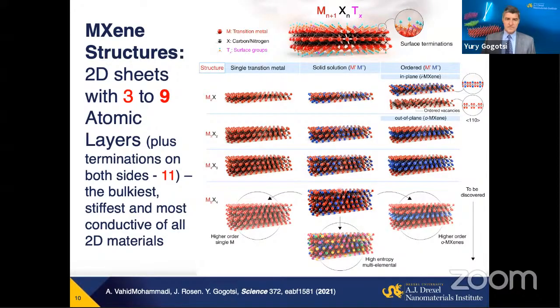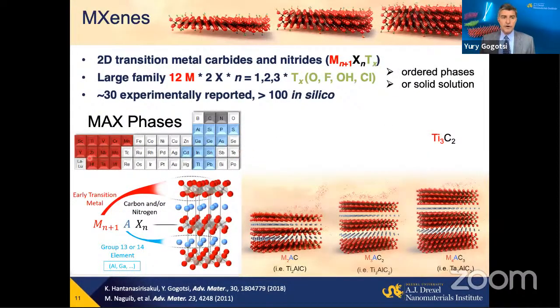So we're still in the beginning. There is plenty of room for synthesis. Many more carbides and nitrides have been reported. Also, so far, most MXenes have been produced by selective etching of the A element from so-called MAX phases, and this is actually how the name MXene came from. A stands for one of those elements like aluminum, silicon, gallium, which are typically etched here. There are also layered carbides, for example, aluminum zirconium carbide, hafnium aluminum carbide, and you can etch the entire aluminum carbide layer away. But you need layered precursors.